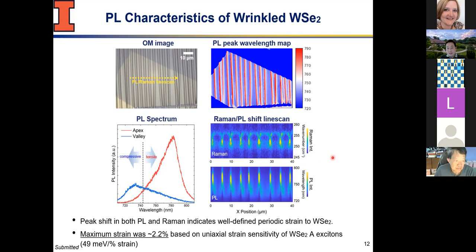And you can use Raman spectroscopy to also confirm it's really the lattice strain that we're dealing with. In this case, you look at the shift at the apex and valley, which demonstrates there are different strains applied to this material. That's consistent with what we measure with PL and what we expected from what was previously demonstrated.